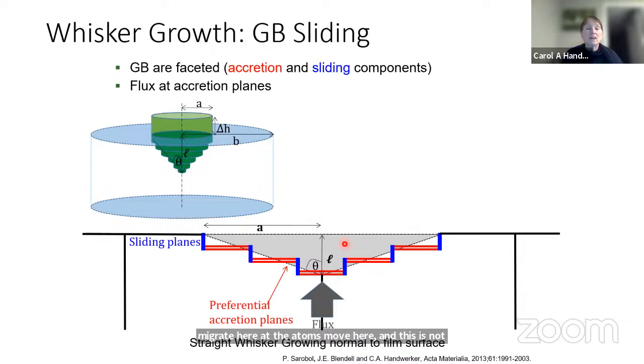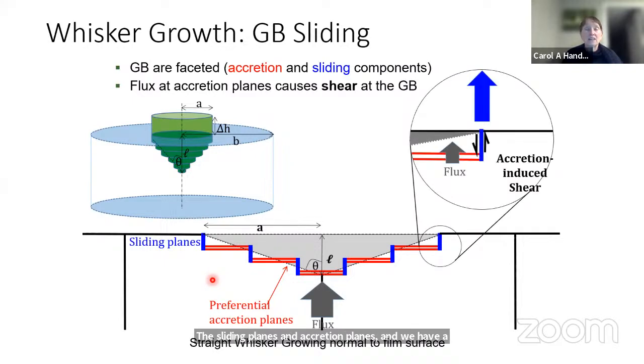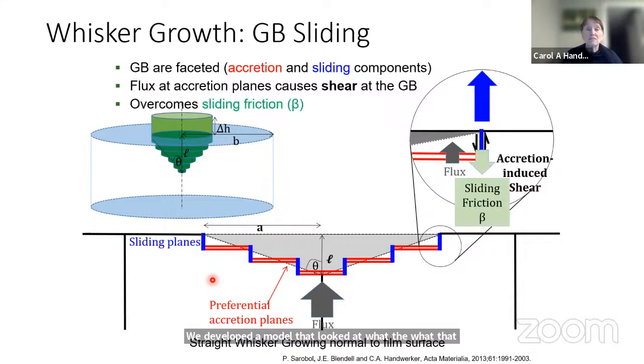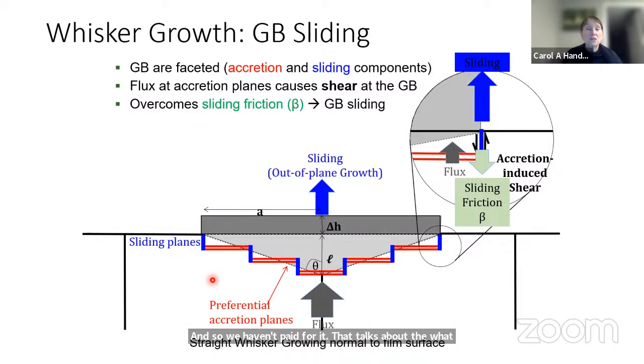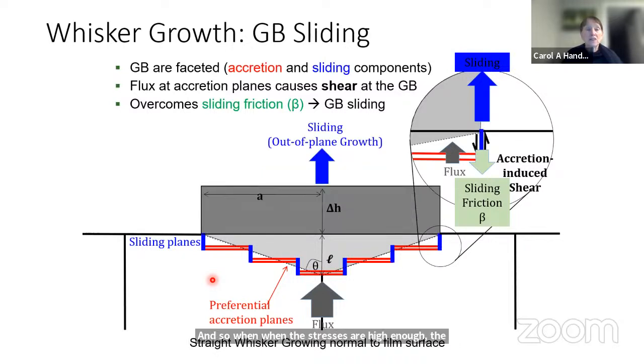And so we took this a little further, having sliding planes. So these are the sliding planes and accretion planes. And we developed a model that looked at what that balance would have to be in order for whiskers to grow. We have a paper in Acta Materialia that talks about what those transitions are. When the accretion stresses are high enough, then we get out-of-plane growth and sliding out of grains. This is grain boundary sliding, limited Coble creep that causes whisker formation.